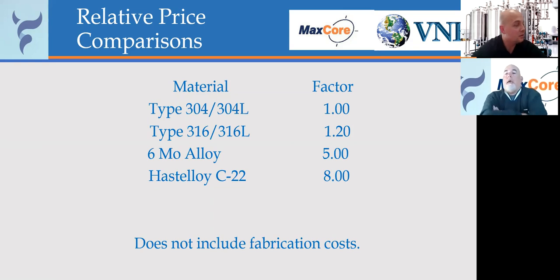That's certainly an option. Some companies have used duplex alloys interchangeably with the 6 moly alloys. As far as corrosion resistance, they're along the same lines as a 904L stainless steel. Do I see them becoming more common? No. The reason I say that is because right now they're being fabricated for the commercial market, not for the sanitary market. The volume is not there at this point in time. Could they be modified and made to be used for sanitary? Absolutely, but you're talking about a lot of costs in doing that.